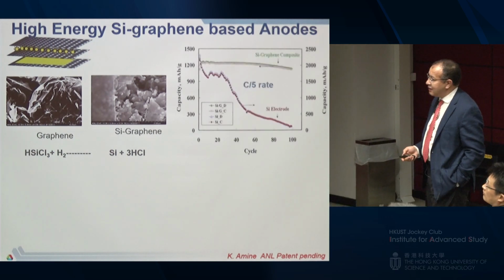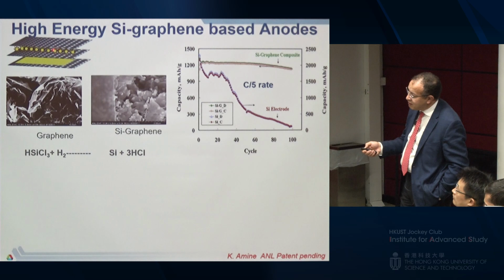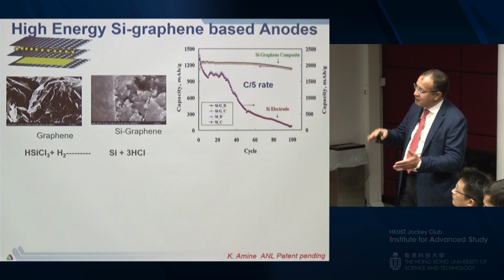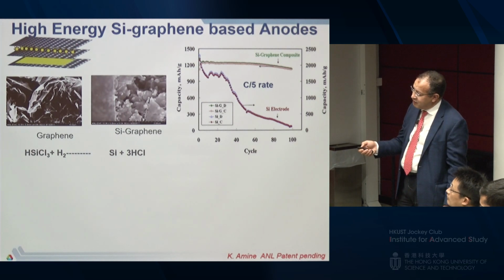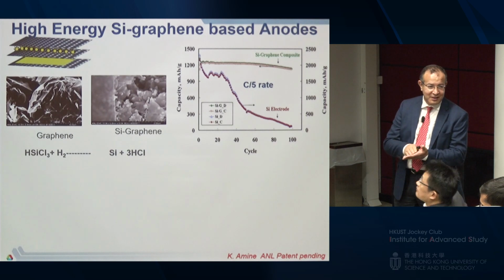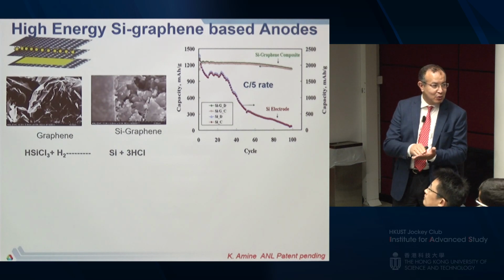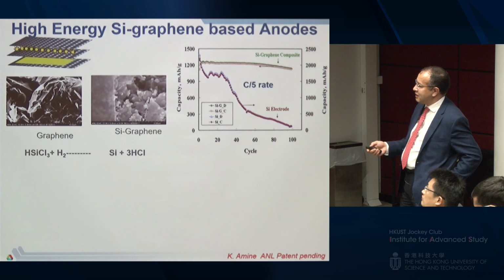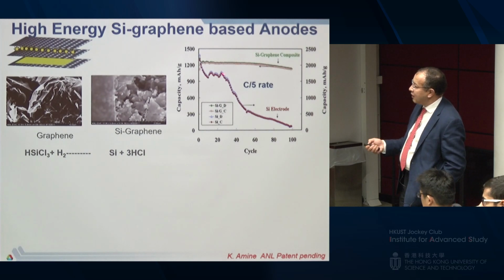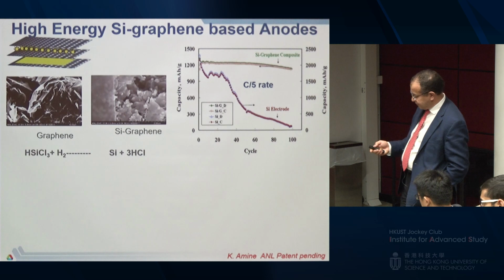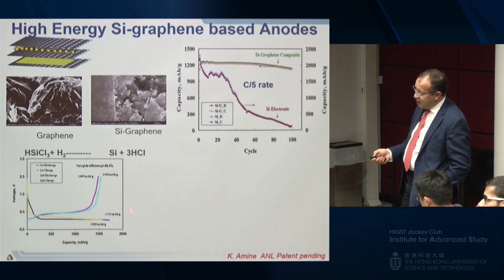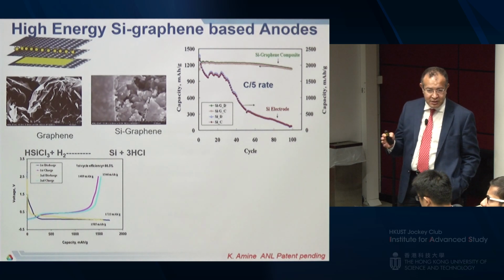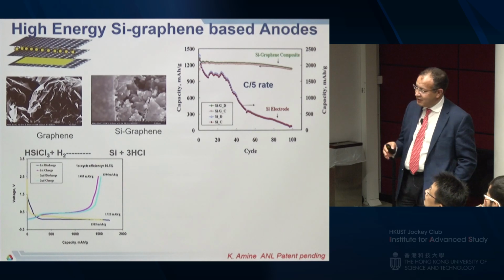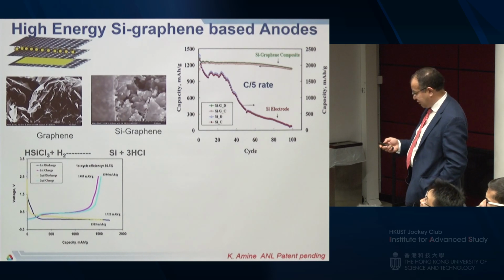So the idea here is when there is cracking, with the pressure of the cell, those sheets, which are conductors, will collapse on those cracked particles and keep conductivity. So you don't lose, you don't isolate the particle. And here is an example where you can see without and with the graphene sheet. We're also seeing, this is another issue that I'll talk about, the efficiency is better, it's only 85%, but it's not as good as carbon. Carbon is almost 98%, and that creates another issue that we'll come back and talk about.